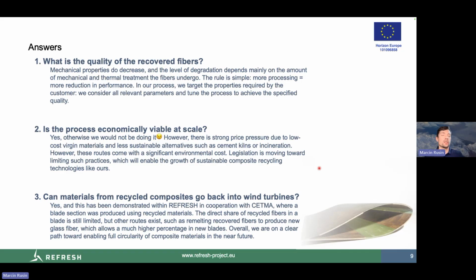That's also why it's very important to understand the requirements of the market, because then we are able to adjust our processes in a way to minimize the impact of our processes on the fiber quality. So by knowing exactly what our customers are expecting for the fibers, we can tailor the process in the proper way. Yes, but we need to be aware that the recycled fibers have some lower mechanical properties compared to the virgin ones. Is the process economically viable?